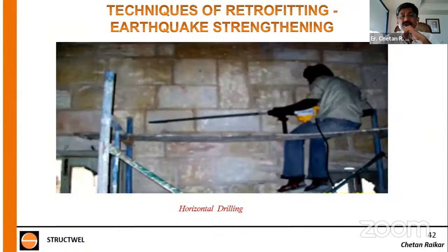We also drilled, what you see is a 5 feet, 1.5 meter long drill. So we were able to drill three stones together, put a mild steel pin. Why we use mild steel? Because Morbi does not have corrosion. If it was Mumbai, we would have used stainless steel. Mild steel pins were used, 8 mm or 10 mm, depending on the diameter. And the annular space was filled up with epoxy.